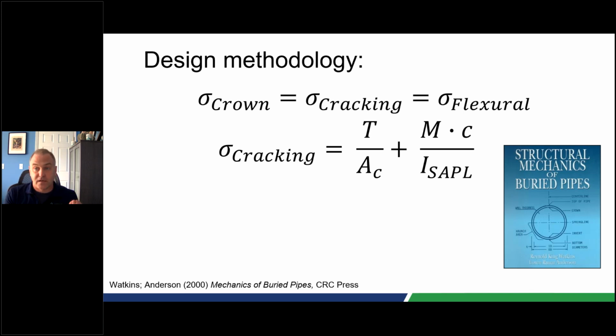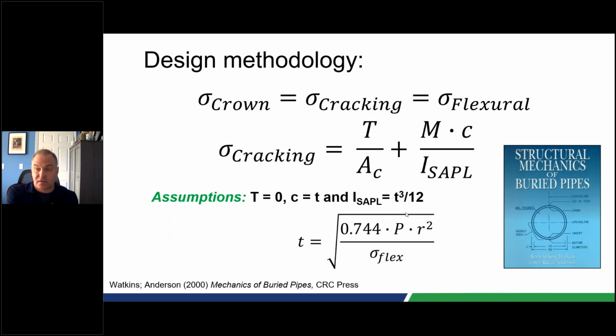So you get a stress at the crown, which is the stress of cracking, which in our view is equal to the flexural strength of the material. We set those equal to basically a standard moment analysis of the system with thrust. And we have assumed in this case that the thrust is equal to 0, that the neutral axis is at the lining, which you see here is c equals t, and that we use the standard section modulus. That will reduce to the equation you see on the screen, where you can determine the thickness based on the load applied P, the radius of curvature at the crown of the material, and the flexural strength, and then you can apply safety factors to your load as necessary.